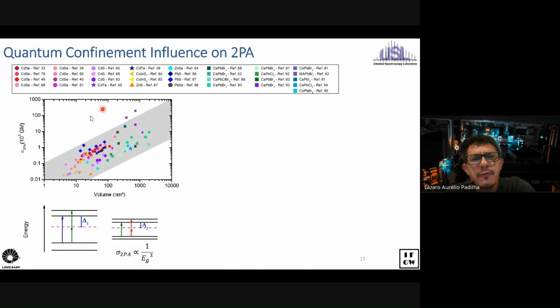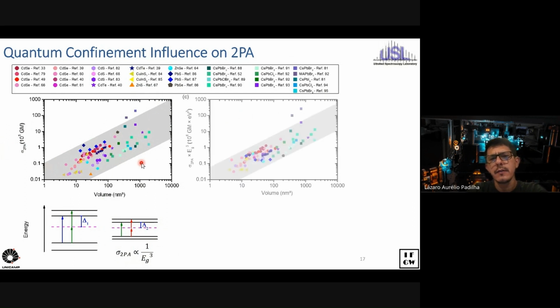So to make a fair comparison for this data, we take this and correct by the band gap cubed, and this becomes a much narrower distribution, which surprises us because it kind of indicates that what is really important is the size, not really the material it's made of. And they nearly all fall within an order of magnitude within all this dependence here.